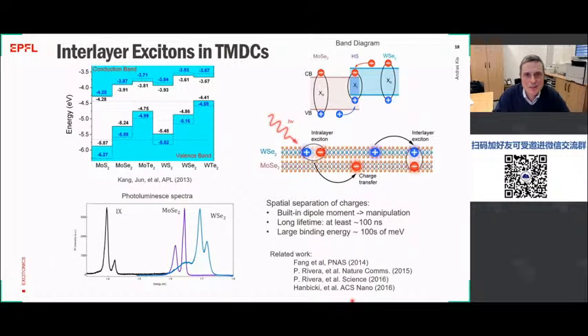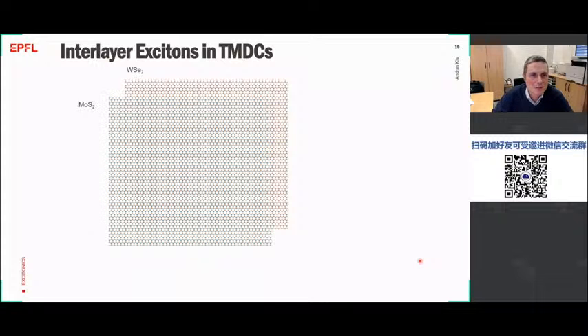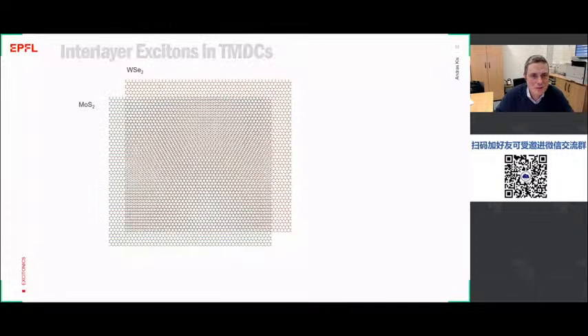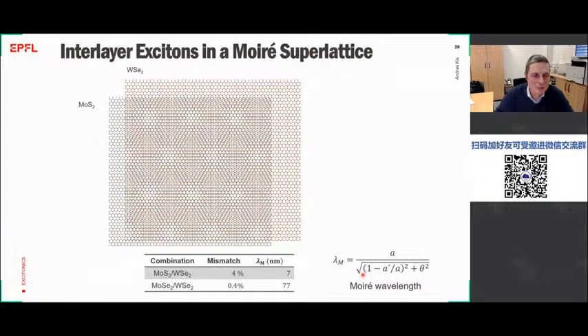Now, this picture is also somewhat oversimplified because it corresponds to the situation we would have in, let's say, regular bulk semiconductors. In the case of 2D semiconductors, the fact that we can take any kind of semiconductor and put it on top of any other semiconductor without respecting conditions like lattice matching also means that we now have additional degrees of freedom, or complication, in the transition metal dichalcogenide heterostructure. So what basically happens is that due to the presence of a lattice mismatch, your picture becomes a little bit more complicated. There is a small possible lattice mismatch, which can generate this Moire superlattice in the 2D heterostructures.